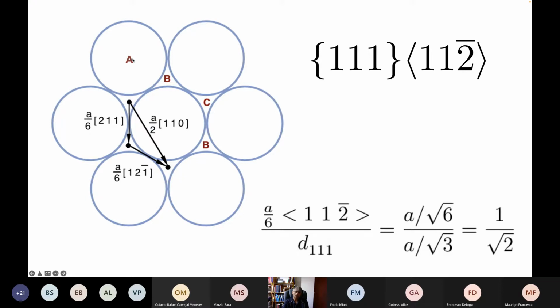The close-packed planes are stacked above each other in the FCC structure of austenite in a sequence A, B, C, A, B, C. Now, what do we mean by that? Well, if in this particular plane the atoms are located at positions A, then there is a sort of a dip in between these three atoms, which is a position B, where the atoms in the plane above can lie, or in a position C. If I translate just from A to A, that doesn't change the crystal structure, okay? So that is simply like slip happening along the 110 type directions. A translation through that vector doesn't change the crystal structure.